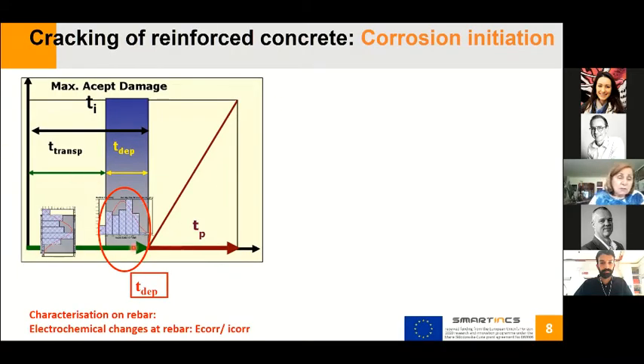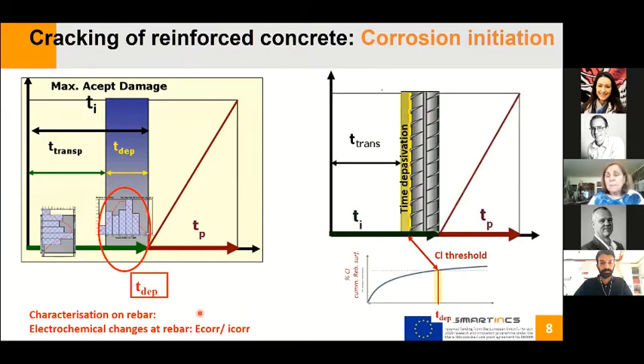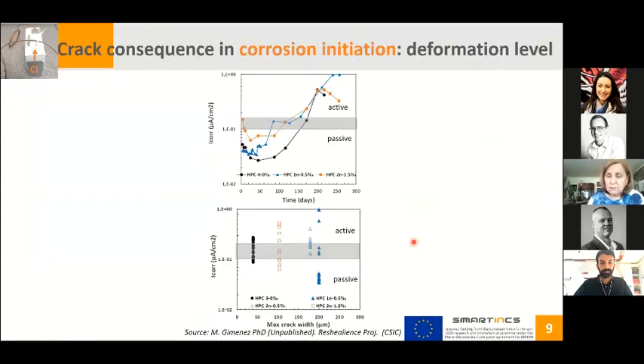For the initiation of corrosion, we need to deal with the moment that corrosion is initiated, so the depassivation moment. So we need to characterize the rebar and use electrochemical techniques to identify when the corrosion is initiated, using either corrosion rate or corrosion potential. To remind again, in this situation the aggressive agent is reaching the reinforcement, but now what we need is the accumulation of this aggressive agent until the corrosion is initiated. This is what we identify as the chloride threshold.